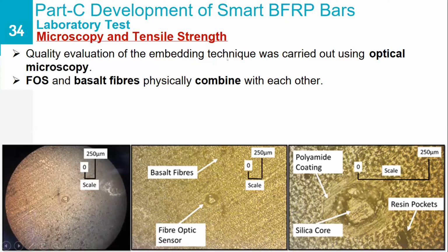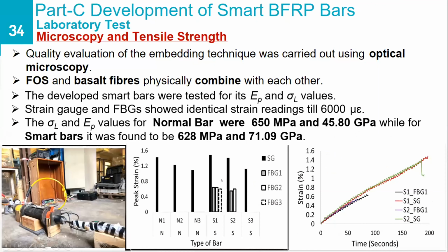So the quality evaluation of the embedment technique was carried out using optical microscopy, and you can see that this fiber optic sensor has been integrated effectively with the fibers of the BFRP bars. And also we have done some other tests. So we have basically tested these bars with some strain that has been applied and measured also using linear potentiometers, and you can see that the strains recorded by the two measuring devices are quite close, although the strains recorded by the LPs are quite higher because the fiber optic sensor did not have the capability of recording higher strains.